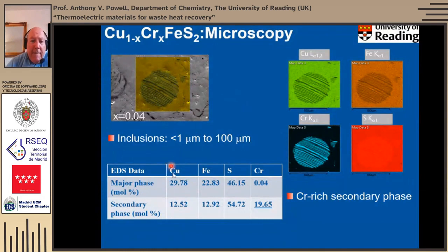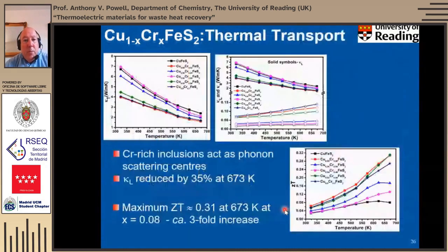And we found that actually the EDAX, or the energy dispersive X-ray data from the microscope, tells us that whilst the major phase is consistent with a chromium-doped chalcopyrite, these inclusions, this secondary phase, for instance, is a chromium-rich secondary phase, and we think that is what is affecting the carrier concentration in a non-systematic way, because it will depend on things like thermal history in terms of the formation of those inclusions, and we think that that is actually what's causing that apparently random variation in the electrical transport properties.